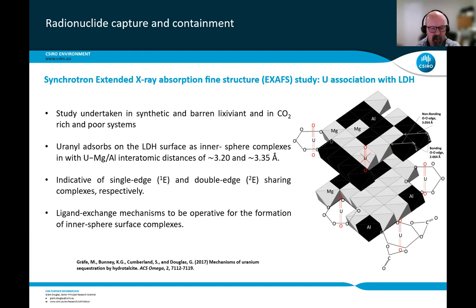And those edge complexations often involve the carbonate or bicarbonate molecules, and they actually form then polydentate ligands at the edges. So it was very much a ligand exchange mechanism on the edge, and that resulted in the formation of these inner sphere surface complexes.